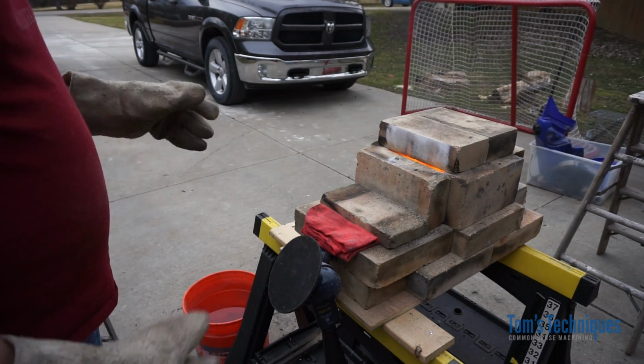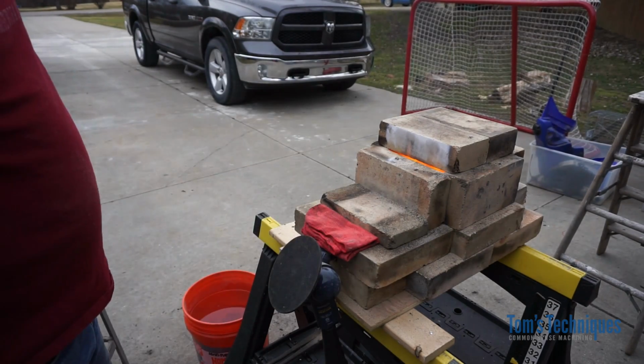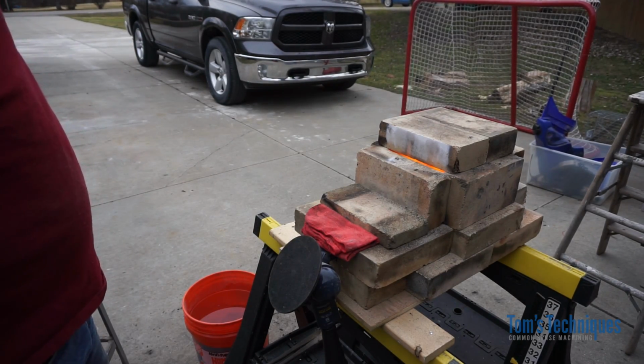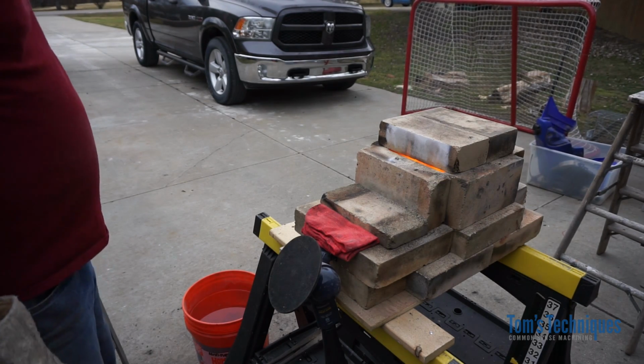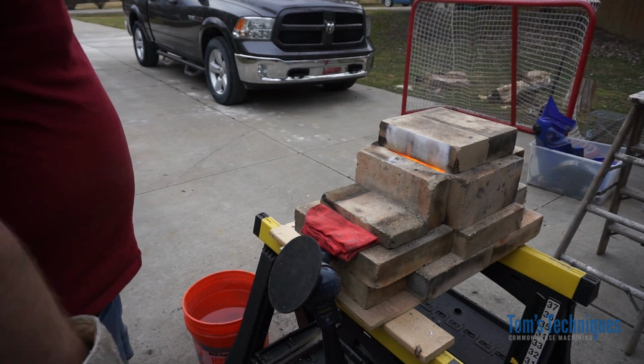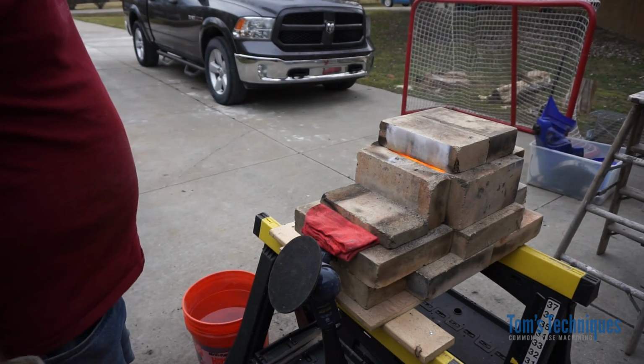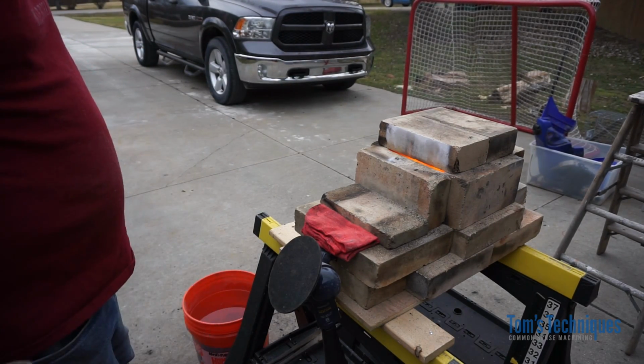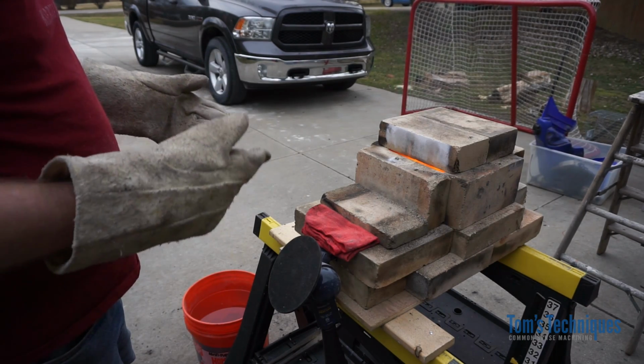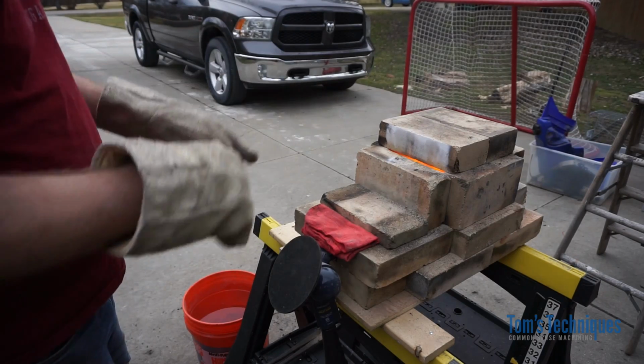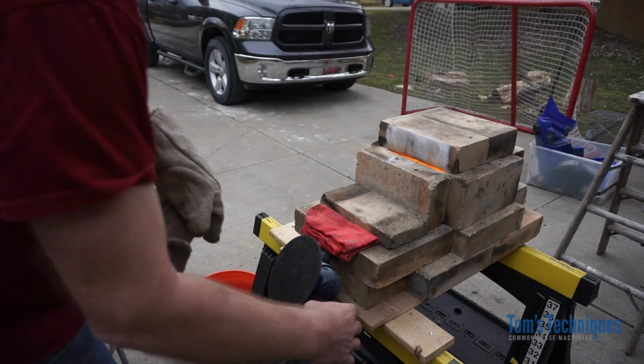So now it's time to quench the part. We're done with our case, our carburizing. The part's got probably, like I say, 10-15 thousandths of high carbon layer on the surface. So now, while it's nice and orange red like this, you want to open up the envelope, take the parts out and quench them. You want to keep them hot until they hit the water. So I'm going to leave it right in the furnace. We'll just shut the air off.